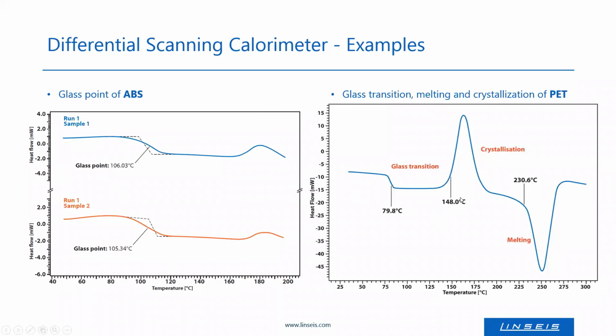On the right, you see a summarized curve of PET. Here you see at around 80 degrees Celsius the glass point, and at 230 or 231 the melting starts. So you see here a rather broad melting peak, and you also see in this graph the crystallization. This information is important for finding the optimum printing property settings.